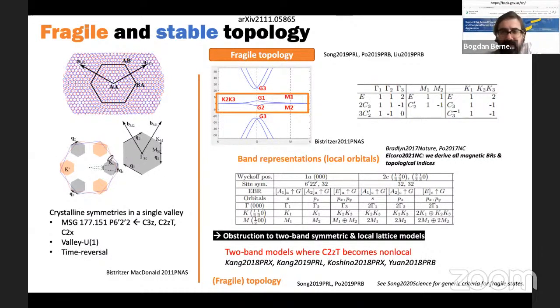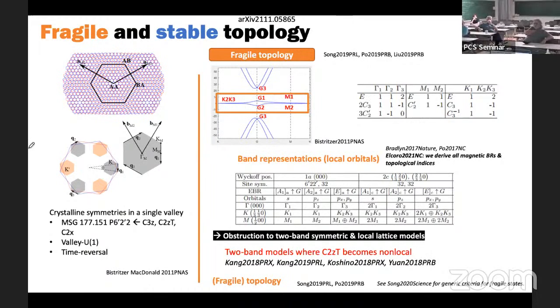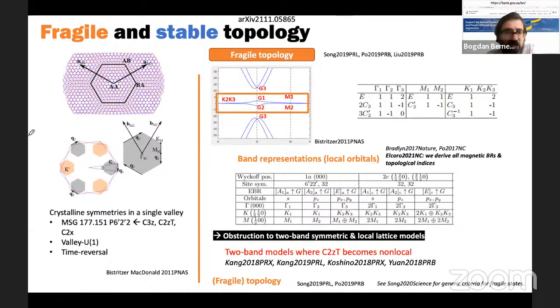So what happens in the Bistritzer-MacDonald model of twisted bilayer, or I would say not just in this model, but in all this class of models of twisted layers with a small angle, is that a new symmetry appears. And this symmetry is an emergent symmetry, and it's a valley symmetry. And I can explain really quickly why it appears, because basically you form a new Brillouin zone, and this new Brillouin zone has its own valley, and to couple it to the other valley of the original graphene lattice, you need to tile this small Brillouin zone many times over. And to tile it many times over means a large order in perturbation theory.